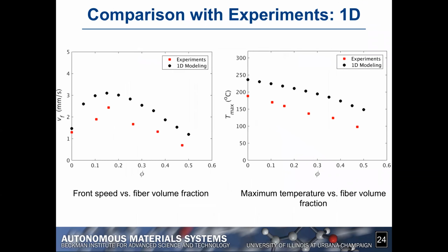Now, how does it compare with experiments? You have here these two quantities: the speed of the front versus fiber volume fraction on the left, and the maximum temperature versus fiber volume fraction on the right. The black symbols are the numerical models, the 1D result that I presented earlier, and the red square symbols correspond to experimental observations. We can see that the model captures the basic trend of the experiments, meaning first the increase, followed by the decrease in the speed of the front versus the fiber volume fraction. However, it tends to overpredict the values that are observed experimentally.